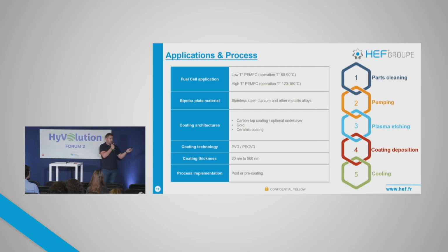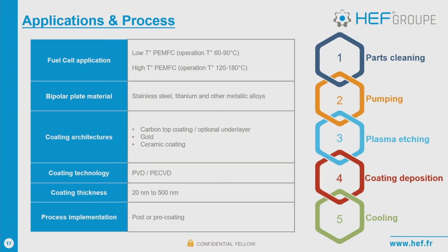And we are doing this coating in 5 steps. So first we clean the part. After we put it in the equipment, we pump all the air out of the equipment. We do a plasma etching to clean the surface. After we make the coating, which is a carbon-based coating. And after we cool the part and it's finished, you can send it to the OEM or the tier 1 to assemble the fuel cell.